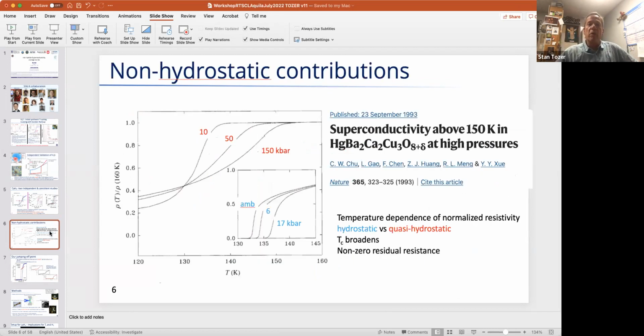And then the last one, I'm going back to the cuprates, because that's what I cut my teeth on, was YBCO. And Paul Chu's group's results on mercury, the mercury cuprate, where when they did hydrostatic studies up to 17 kilobar in a piston cylinder cell, they saw reasonably sharp transitions and zero resistance. But when they extended that pressure range up to 150 kilobar so that they could push TC out, you see the issue becomes you're at 10 kilobar in the diamond cell, reasonably narrow transition, but not as narrow as one has down here with the hydrostatic pressure medium. And then as one pushes out to 50 and 150 kilobar, it's non-zero and it's very broad.